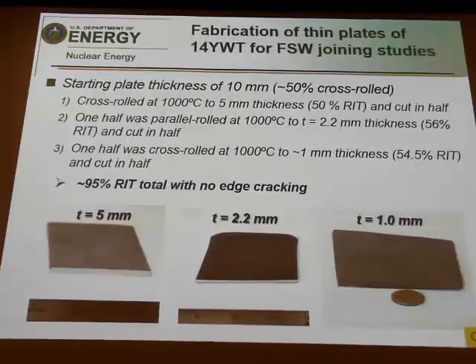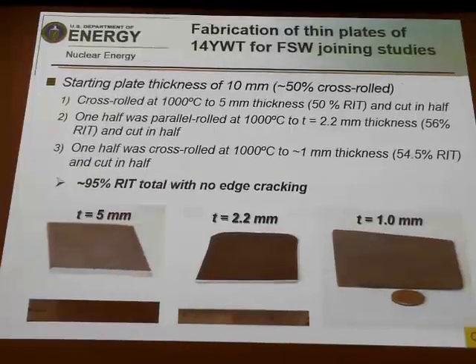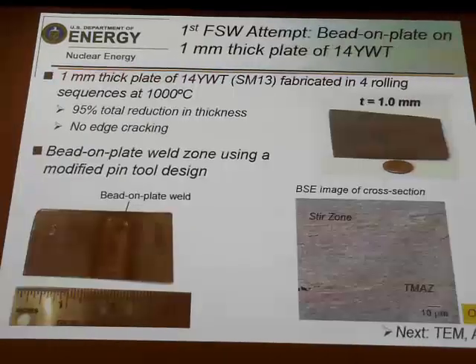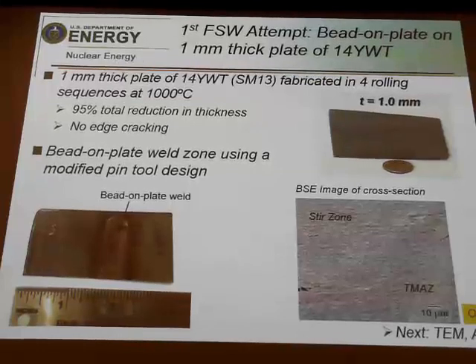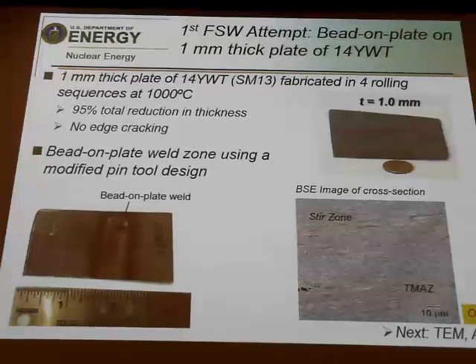The reason why we wanted to take it down to 1 millimeter in thickness is that we're trying to test the way you'd weld this material on a thin sheet, and one of the processes is friction stir welding, which mixes the material without melting it. If you were to melt it, then all the oxides are going to collect, and you'll have large oxides in the material again. So you want to do this without actually melting it.